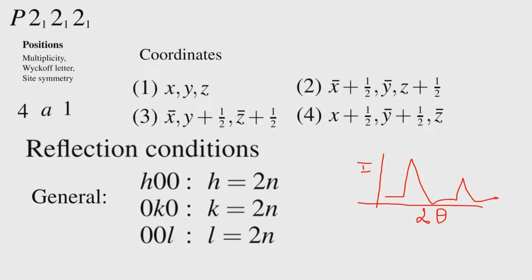The x axis will tell you where the 2 theta value should be for a given peak, assuming that it is all unique. Then we can determine where these peak positions come, and this gives us the information on the d value and therefore the cell dimensions. So, we can determine a, b, c, alpha, beta, gamma using that information. The intensity tells us the value of the intensity associated with the diffraction coming from that particular plane HKL. So, we determine I of HKL.